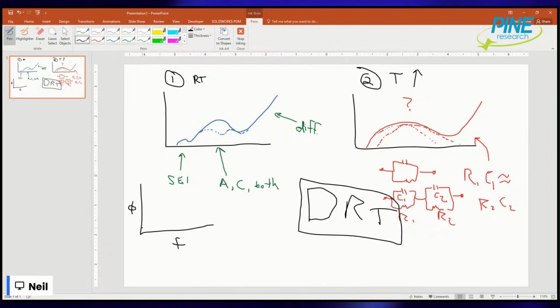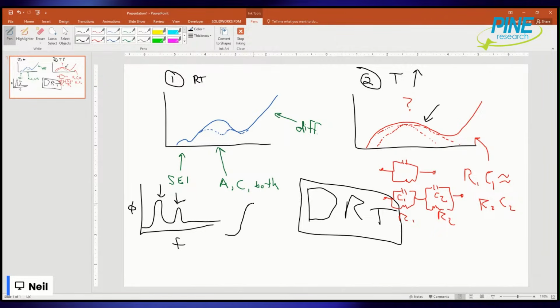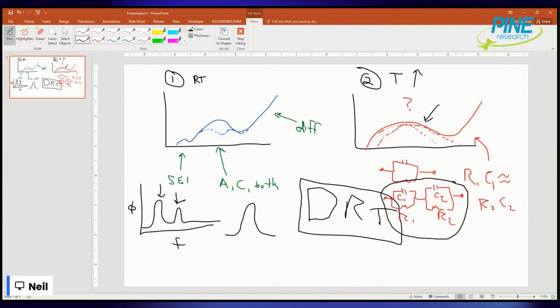But my point is, if you do DRT and you get 2 peaks, then that is telling you, oh, I have 2 processes here. The distribution of relaxation times has the benefit of being able to find these distinct peaks. If the DRT gives you just 1 peak, then there is only 1 process. So that's what DRT can help you understand. It can't necessarily help you model it from the circuit fitting perspective, like these RCs, because if it's one semicircle, there's basically infinite possibilities for the Rs and Cs. So it can be almost impossible to fit. But the DRT can help you know if there are at least multiple processes.